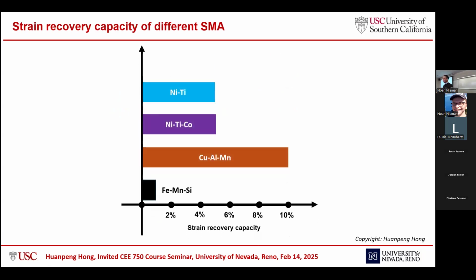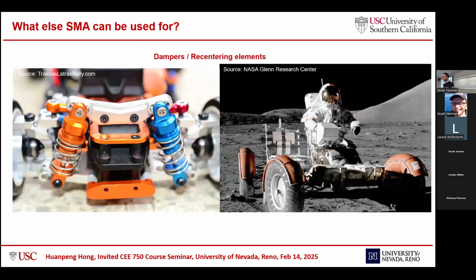And here's the strain recovery capacity of different shape memory alloys. For conventional nickel titanium alloy, it can generate a strain recovery of around 5%. For nickel titanium cobalt, almost the same, a little bit higher or lower than around 5%. For copper aluminum manganese alloy, it's around 10%. And for iron manganese silicon alloy, it's around 1% or less than 1%. So I briefly introduced applications in actuators.